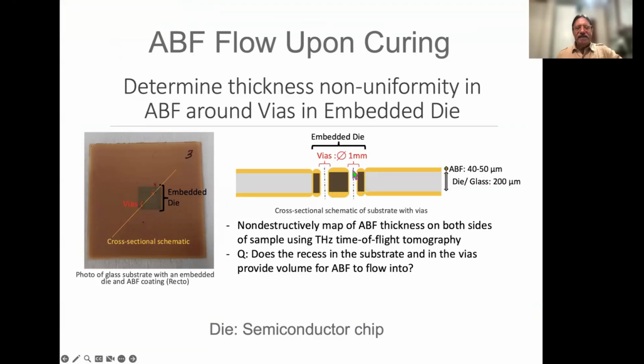The die has vias, rather large vias in it. Here's the glass substrate. The die is dropped into that recess. The recess has to be a little bit bigger than the die to get it in there. And then ABF film is put on the top and the bottom of that assembly. What we want to do is map out the thickness of that ABF film, because that might tell us how the ABF flows while it's cured. And we're going to see that the ABF film after curing is not uniform across this structure.